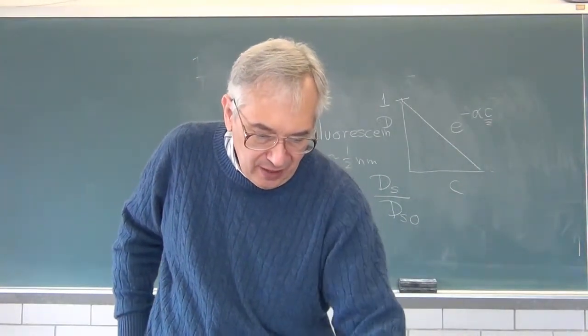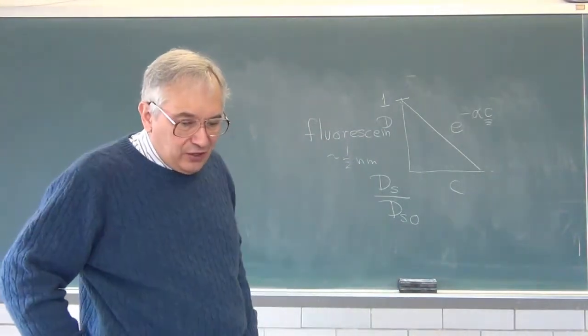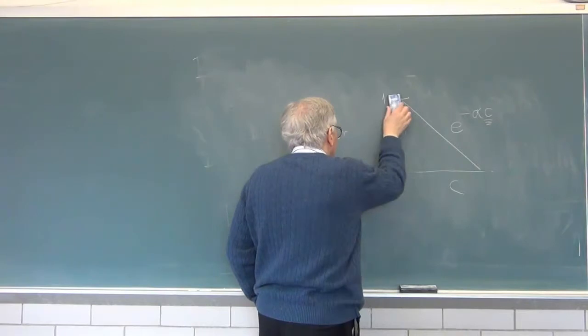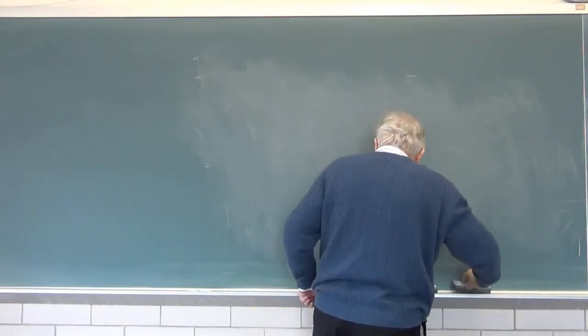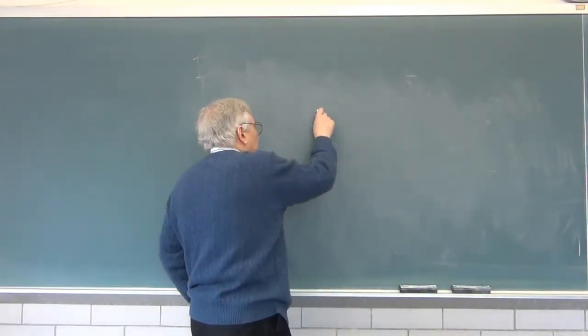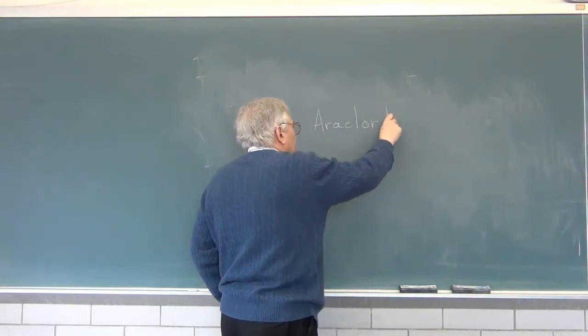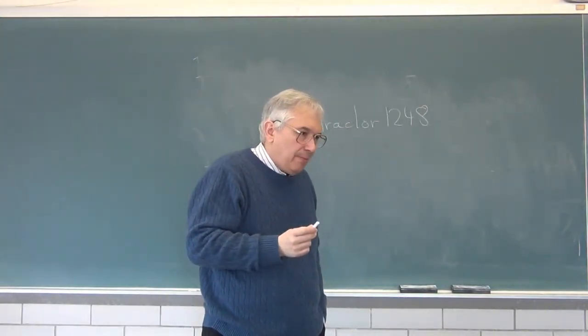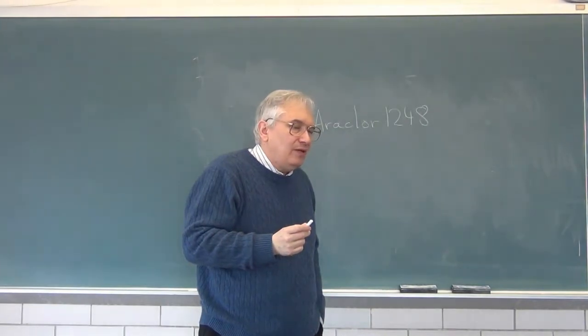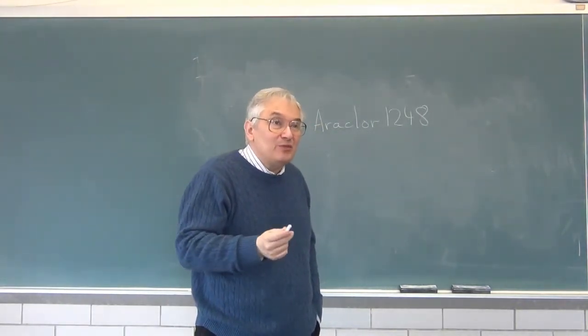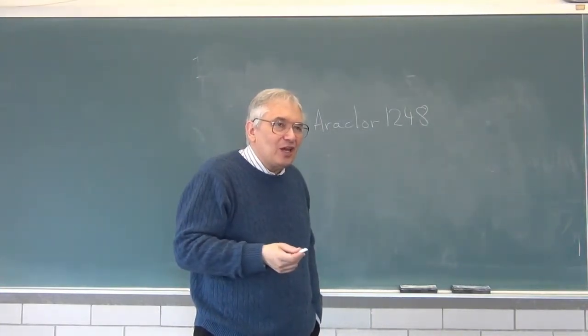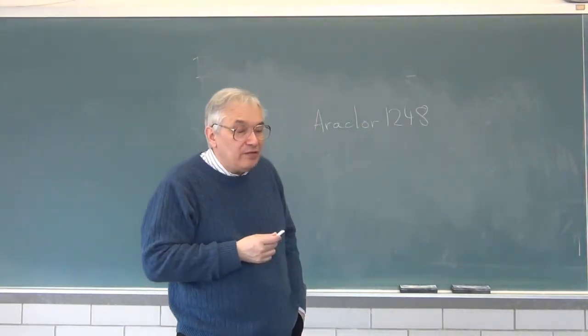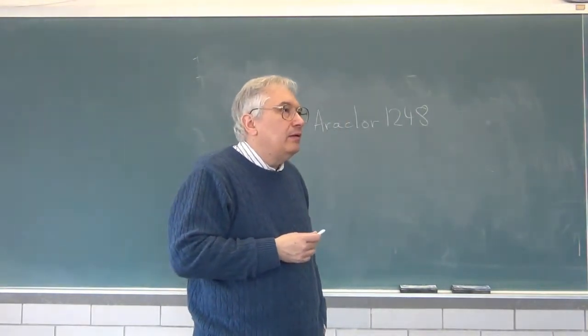Now there's one interesting feature of hydroxypropyl cellulose. Hydroxypropyl cellulose has a liquid crystal phase transition about half way across that graph. The fluorescein diffusing through the HPC doesn't notice that this has occurred, it just diffuses, but there's just a straight line straight through the phase transition. The y-axis is the ds divided with ds0, and that stands for relative diffusion coefficient. We take the diffusion coefficient and divide by the diffusion coefficient of the fluorescein in pure solvent.